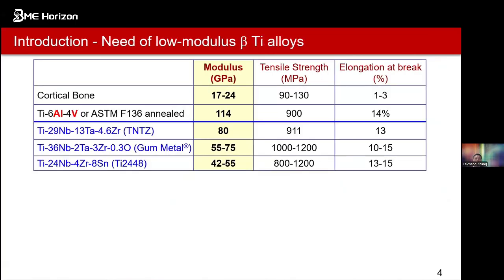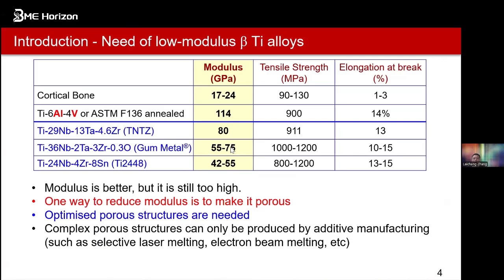Of course, there's another way to do so. We can develop low Young's modulus titanium alloys to match the Young's modulus of cortical bones. For example, TNTZ, Gum Metal, Ti2448. So these famous beta titanium alloys have a very close Young's modulus compared to cortical bones. But this is still higher, so you can see this will go to roughly 30, and this one could double or triple. So even though it's a better or lower Young's modulus, it is still high.